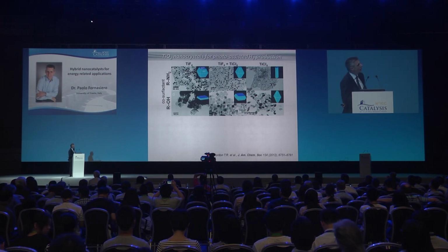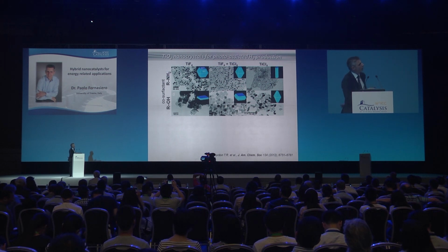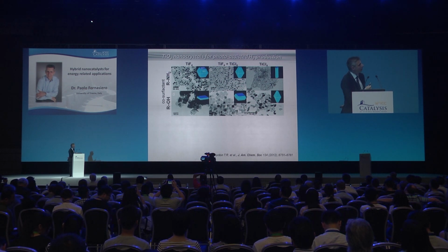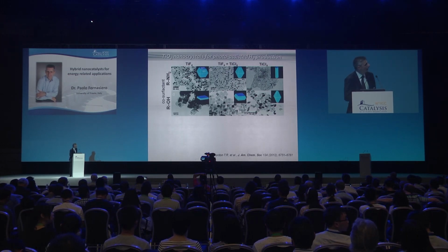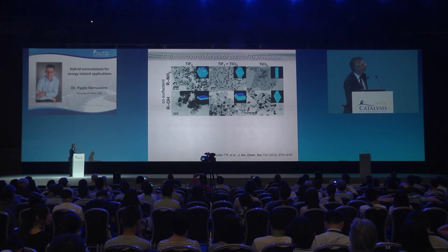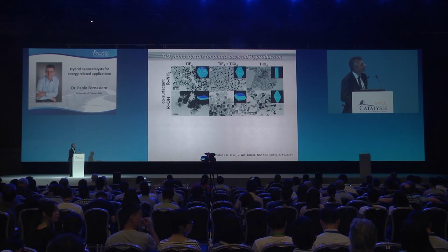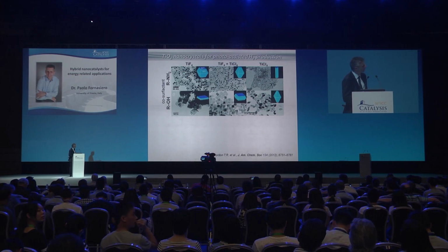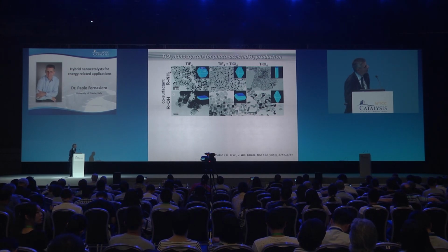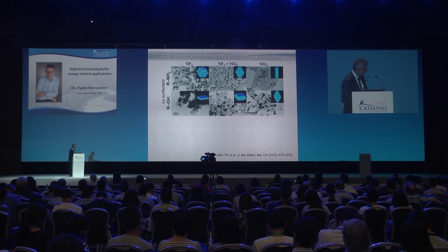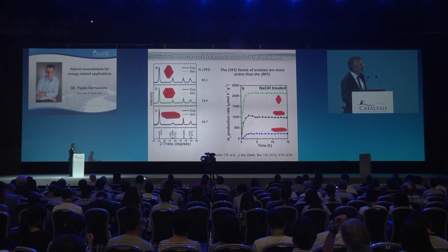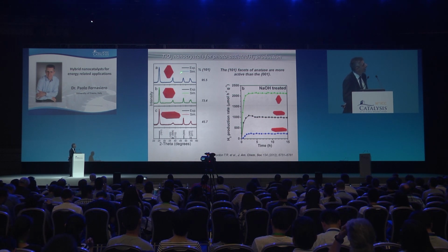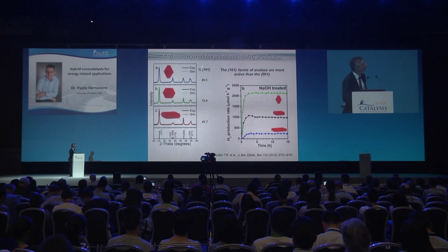Keeping in the photocatalysis area, we did lots of work on nanocrystals with the idea to understand which of the facets is really more involved in the reaction we were looking at. And by playing with the type of co-surfactant and metal precursor, we obtained these nice monodispersed crystals of different phases. This is anatase, this is brookite. I'll come back later on that aspect. And if you look at just the anatase phase, you can have these different shapes having different ratios of the 101 and 001 facets, from pure 101 to a 50-50 mixture.